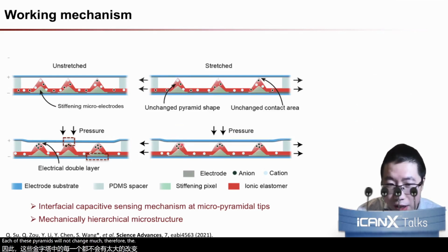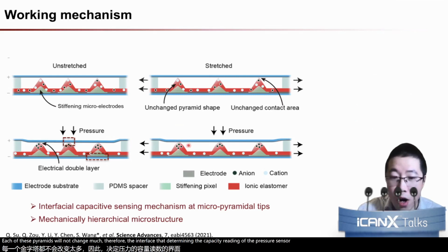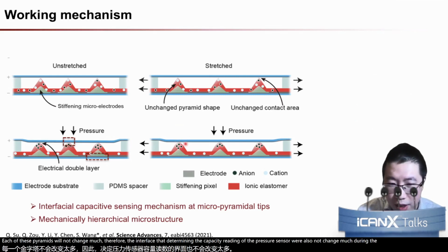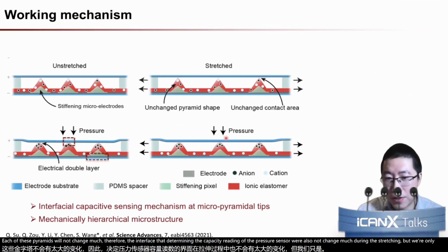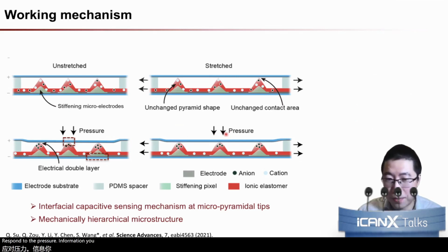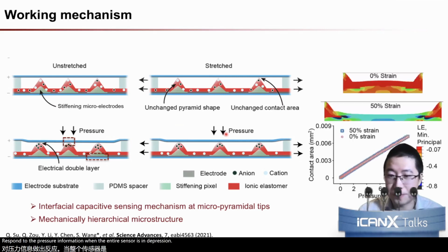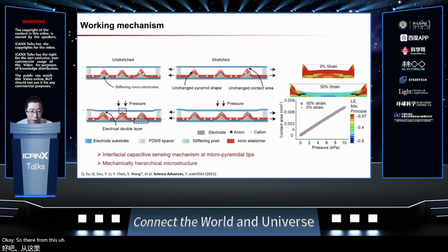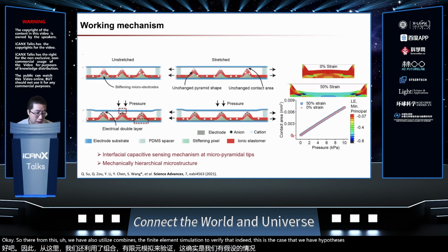Therefore, the interface that determines the capacitive reading of the pressure sensor will also not change much during the stretching, but will only respond to the pressure information when the entire sensor is under pressure. Okay, so from this, we have also combined finite element simulation to verify that indeed this is the case that we have hypothesized during the deformation of the stretching.